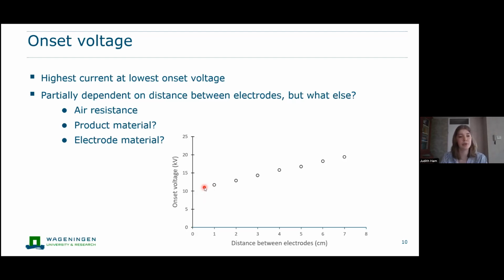also other influences. We see, for example, that the electrode material we use affects the onset voltage, and we see that the product material placed between the electrodes also has an effect. A very wet product is more conductive, meanwhile a drier product is less conductive and therefore contributes more to that minimal amount of energy needed to jump that air gap.